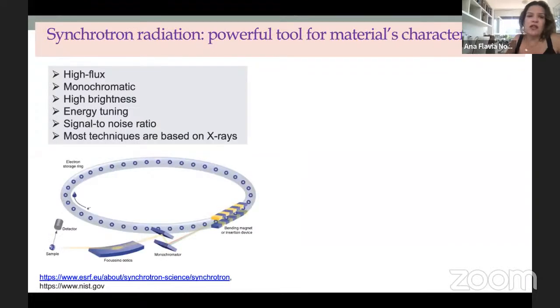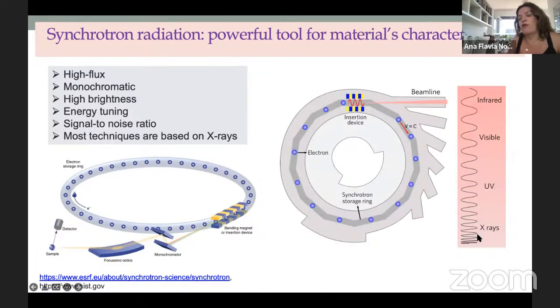So why is synchrotron radiation really interesting to characterize materials? Because it's a high flux energy. For those that are not familiar with the synchrotron, this is the electron storage ring. We have electrons here moving at the speed of light. When these electrons pass through this bending magnet or insertion device, we produce light. This is the synchrotron radiation. Then you can set some monochromators to tune the energy of your radiation, and then use some focusing optics for this radiation to reach your sample. Then you can do lots of experiments here, not only with X-rays, which are of course the most common, but you can also use UV, visible, and I'm showing an example here when we use the infrared.